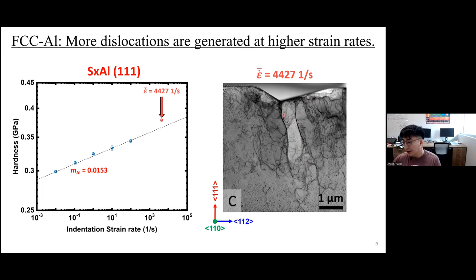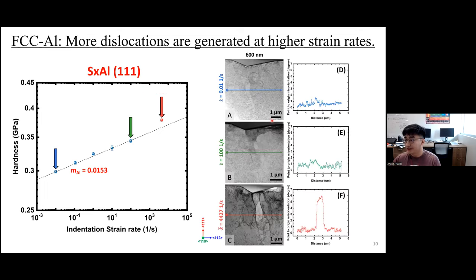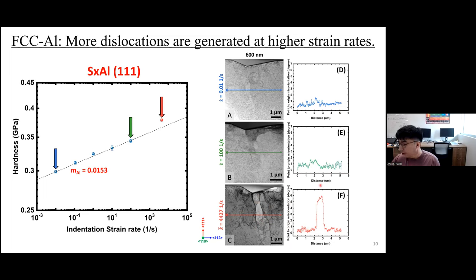To determine the lattice orientations within this dislocation cell structure, we performed a PED test — a small-scale EBSD inside a TEM — which gives the Euler angle at each pixel. We calculated the point-to-origin misorientation across an arrow using the first data point as reference. The cell structure from the impact test gives rise to large misorientations, whereas at strain rates of 100 and 0.01 we found no obvious change in misorientation. This large misorientation is likely related to the increase in local dislocation densities and explains the hardness deviation observed at impact strain rates.